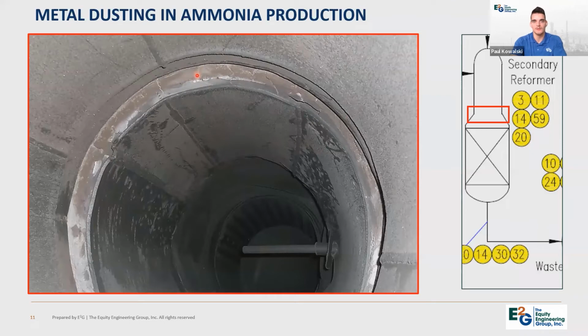So now the refractory is directly exposed to the process. It may be subject to additional damage to the refractory, and then ultimately the 2 1/4 chrome base metal is no longer protected and exposed to those high temperatures, and severe mechanical integrity issues can occur pretty quickly in this case.